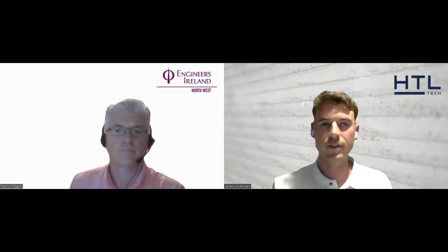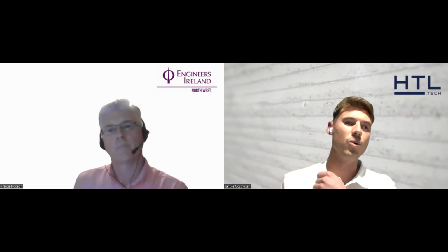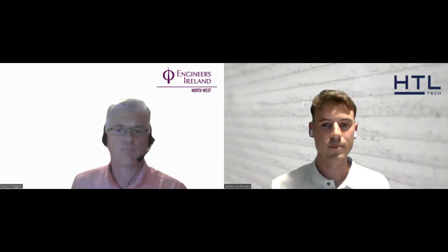Thanks. Salima has asked how the concrete curing is done on these projects. Essentially, after the print, we spray a curing compound onto the surface, which creates a wax-like surface on the concrete. That traps the water in the mix, so it doesn't allow the water to evaporate and the concrete to shrink. That stops it from cracking. And we introduce fibers into the mix. It's a polypropylene fiber in the mix design, which also gives us a little bit better durability.